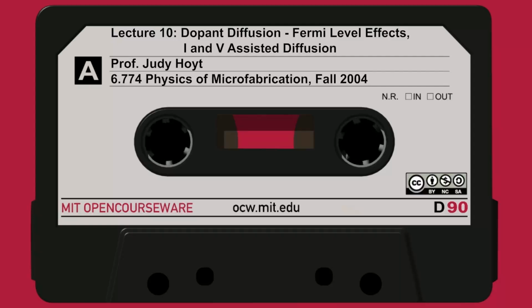If K0 is 1, then it'll arrange itself to have the same concentration on either side. If K0 is 10, it's going to want to have a factor of 10 difference in concentration going from material B up to material A. So this different solubility causes this sort of equilibrium segregation.